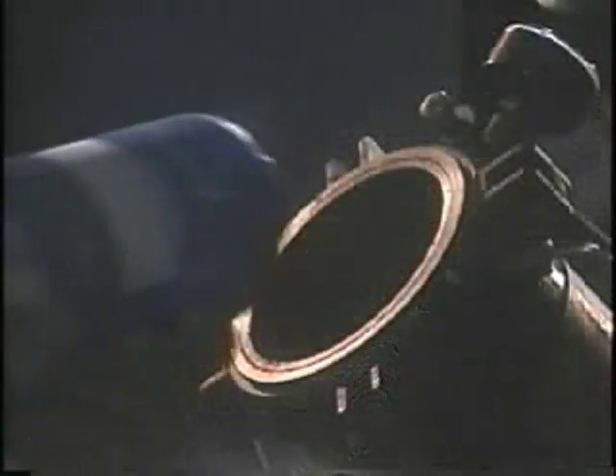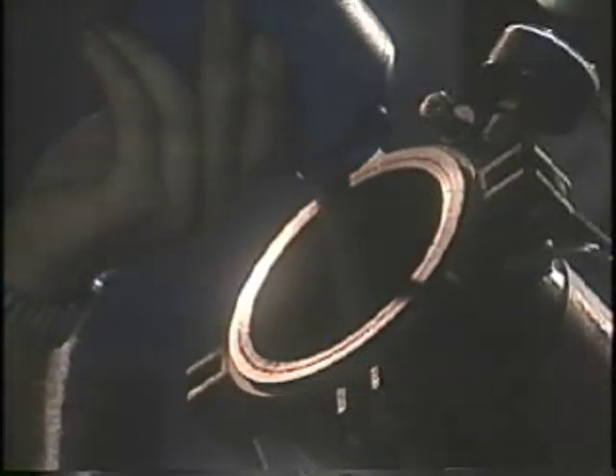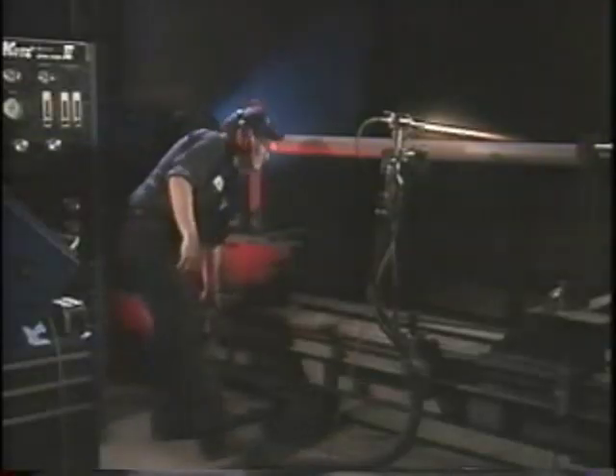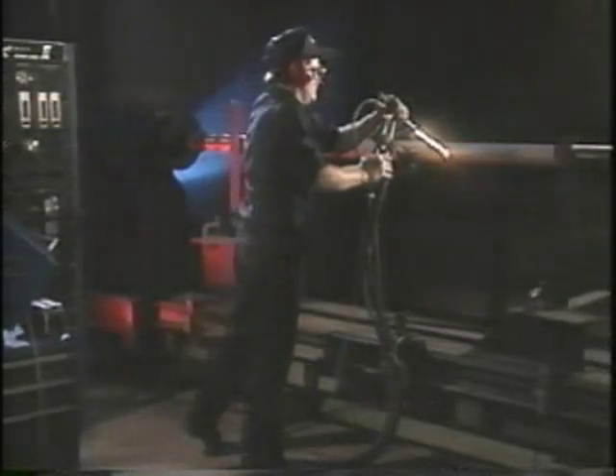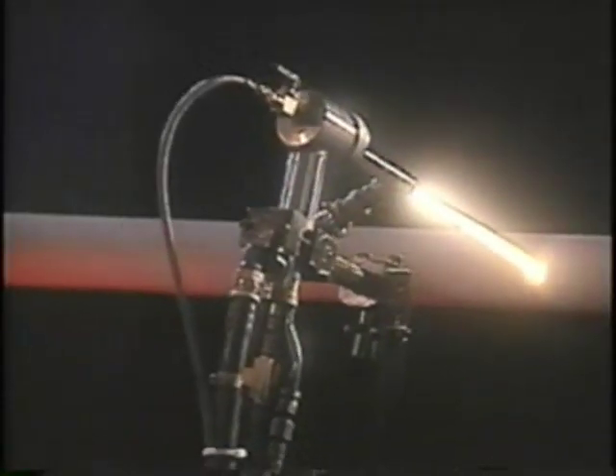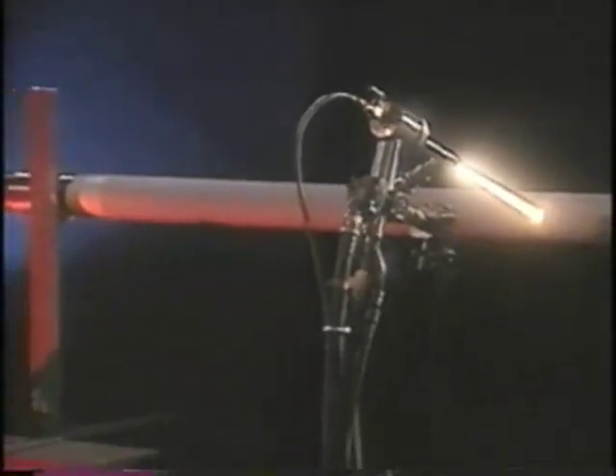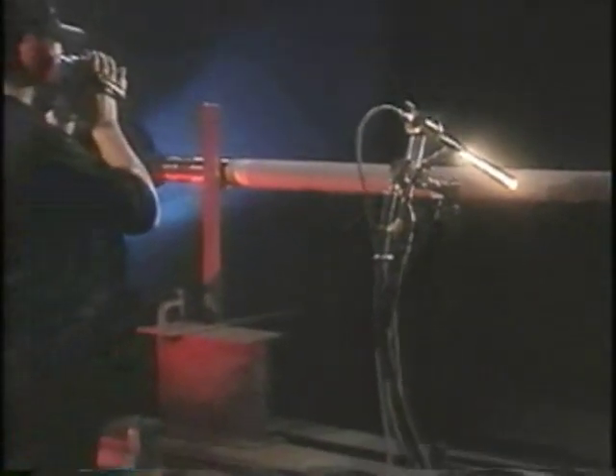The high-velocity coating process has its own special chemistry, with about 20 different blends of material available. This compressor rod, for example, is to be coated with a mixture of 88% carbide and 12% cobalt. If the part were destined for an especially corrosive environment, a nickel matrix would be used instead of cobalt. There is no single ideal coating. The decision depends on the part and the service environment. Temperatures, pressures, RPMs, and chemical exposure are taken into consideration. It's very important that the substrate be held at the proper temperatures at all times during the coating process.